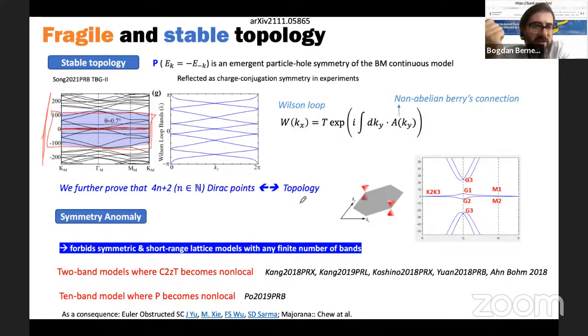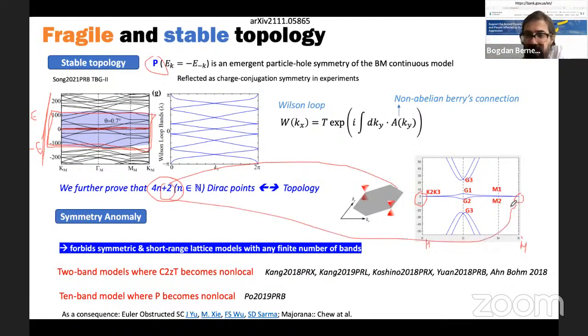So it turns out that the actual key point of the graphene model is the existence of 4n+2 Dirac points in any bands taken between energy E and energy minus E. So if I take any set of bands between energy E and energy minus E in the Bistritzer-MacDonald model of twisted bilayer graphene, or in any small angle model of bilayer graphene with an extra symmetry that's particle hole that's actually also emergent in these models, then I will have 4n+2 Dirac points in these bands. I can never have 4n. And two of them are at the k-moire point of the moire lattice of graphene, at k-moire prime. These are these two. And all the other four can be spread out into the other bands.